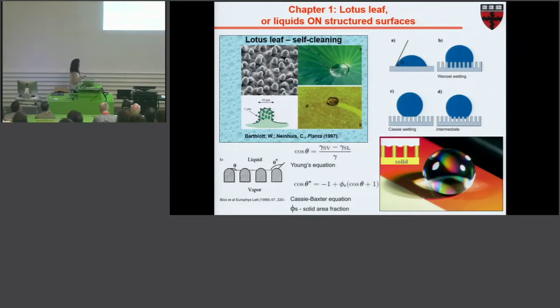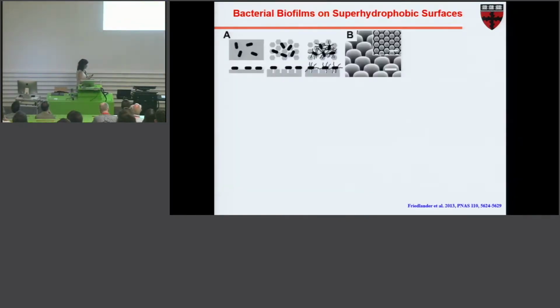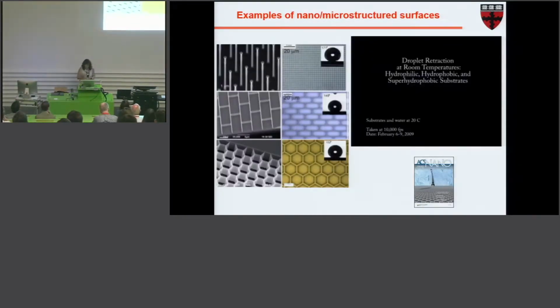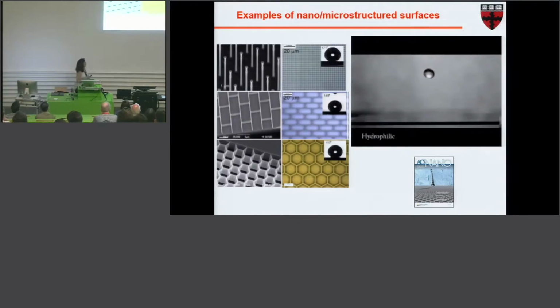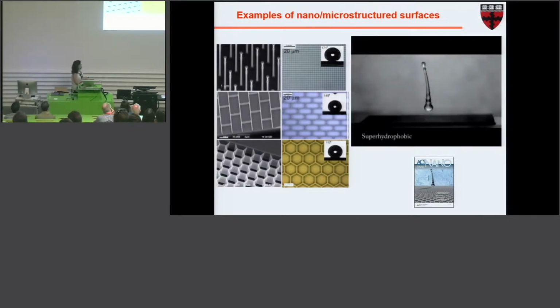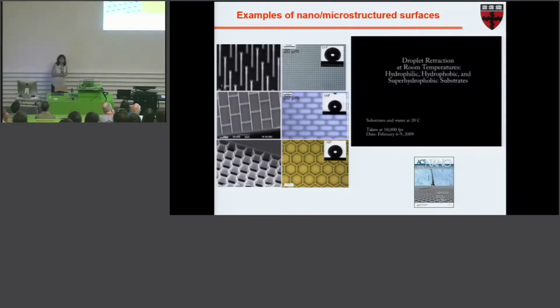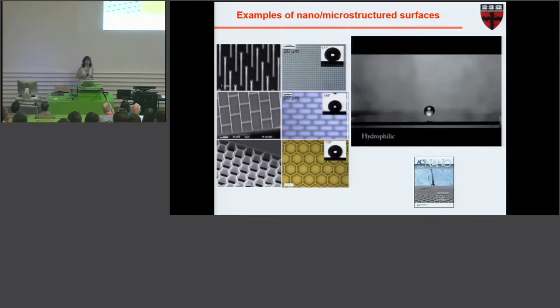So one can use that, of course, as a way to think about new materials that can change their properties, and we can build them in any way we want. But the most important thing is that if we look at the interaction of a droplet of water on a hydrophilic surface, of course it loves it, it spreads and stays. On hydrophobic it spreads, contracts, but it's still always in contact with the substrate. But on a superhydrophobic surface, water droplets would touch the surface and be repelled completely, leaving the surface without contact with the liquid at all.